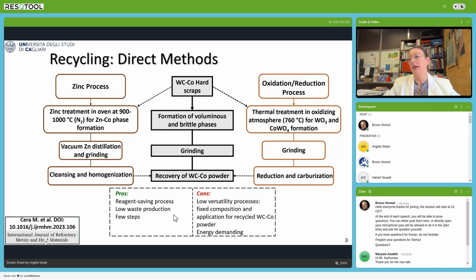On the other side, the main aspect that in some cases hampers the use of these recycled powders is the fact that it's not possible to tune the amount of cobalt and tungsten inside the mixture. So the versatility of the process is lower than the application of chemical approaches. And also the presence of interferences or polluting species inside or on the surface of the pieces is difficult to remove.